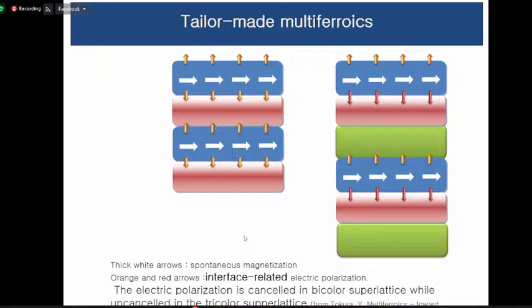Professor Tokura suggests some structures. In his suggestion, he said if the material is like a bicolor, a 2 layer structure repeated, then at the interface the polarization is present, and then the polarization is cancelled because this interface polarization and that interface polarization have the same amplitude but opposite direction. So there is no net ferroelectricity. But if we break the symmetry, then we can find some polarization like this.